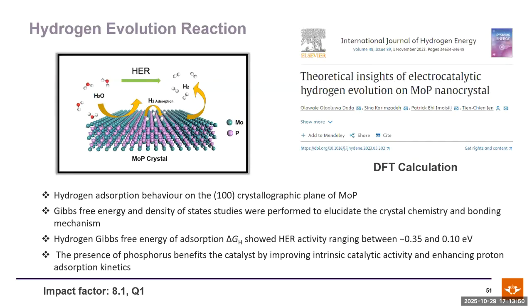And this is another work, but this one is for hydrogen generation. We published it in the International Journal of Hydrogen Energy. It gives theoretical insights into electrocatalytic hydrogen evolution of molybdenum phosphide nanocrystal. This shows the hydrogen Gibbs free energies of adsorption, with HER activity ranging from minus 0.35 to 0.10 eV, which is also quite good. So I think this is one work we can play around with to achieve better hydrogen generation.